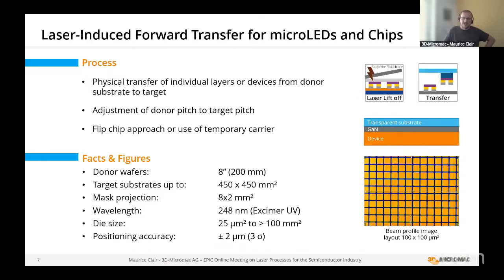And if you do the calculation, how many of those are in an area of 8 by 2 square millimeters, we are talking about a transfer rate of millions per minute, which was the target value for production in the micro LED business, because the basic idea was and is to build very large displays like smartphone displays out of this technology.